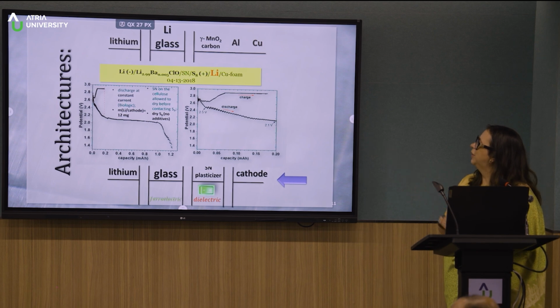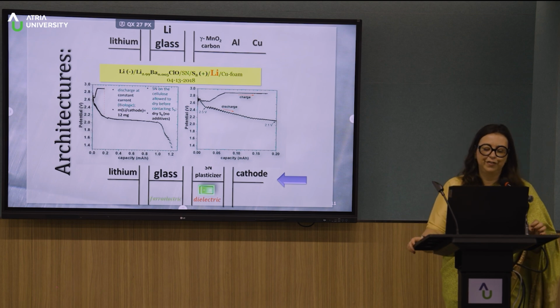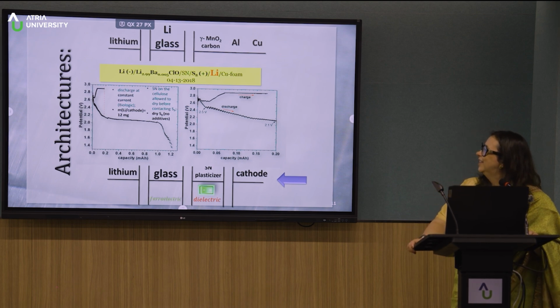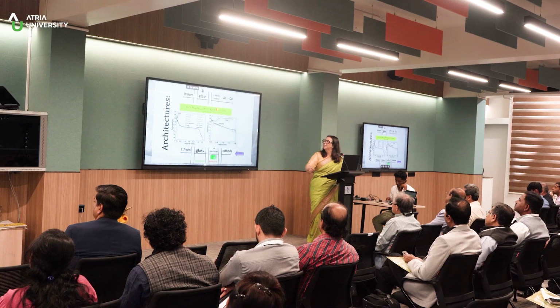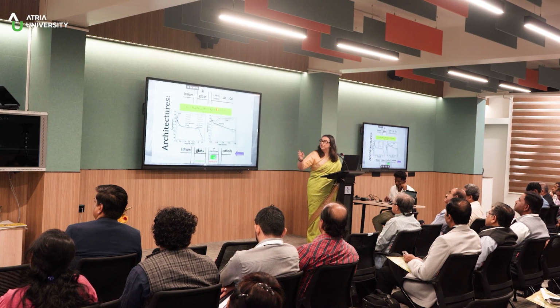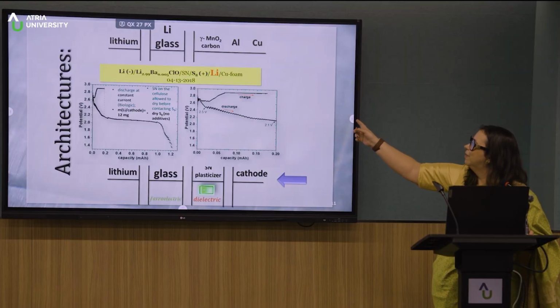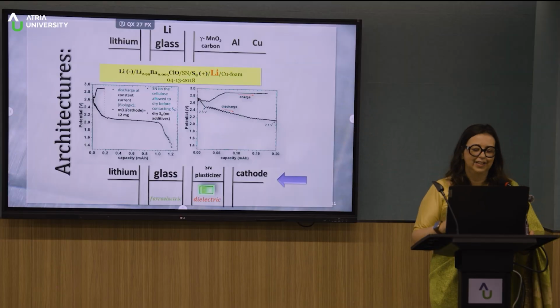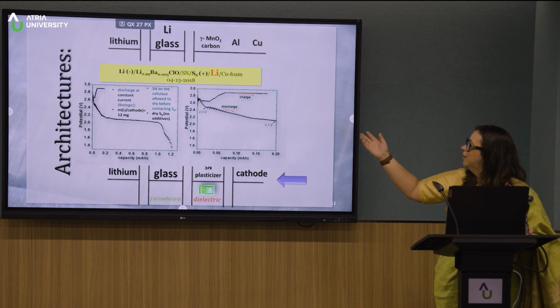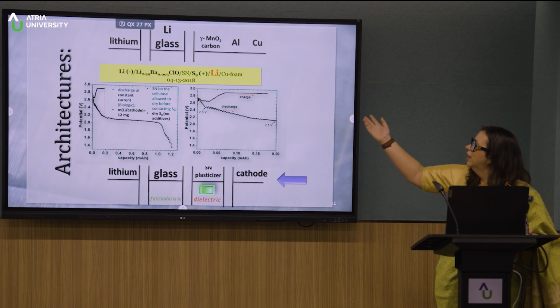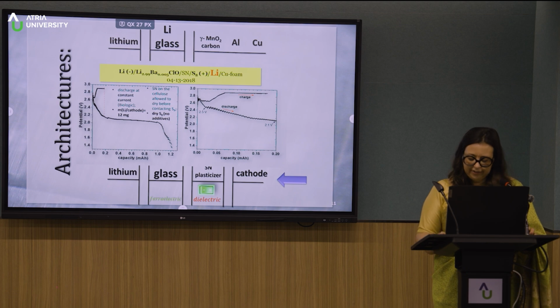And as you see, we could actually discharge this cell for a long time. We made this actually in front of industrials that didn't believe us in the first place. But then, of course, they believed us that we could do a cell with lithium on the positive electrode. Actually, this cell contains more lithium on the positive electrode than on the negative electrode. And this lithium just works as a current collector, a normal current collector.